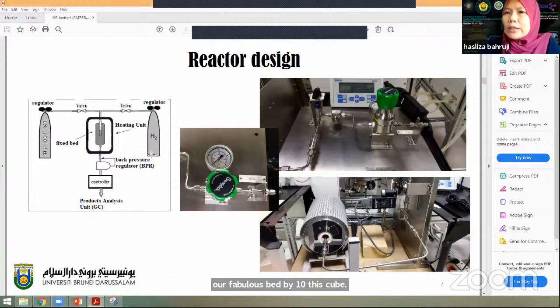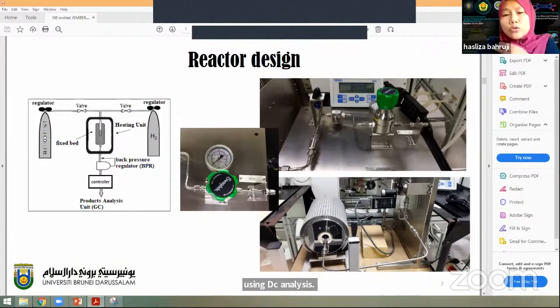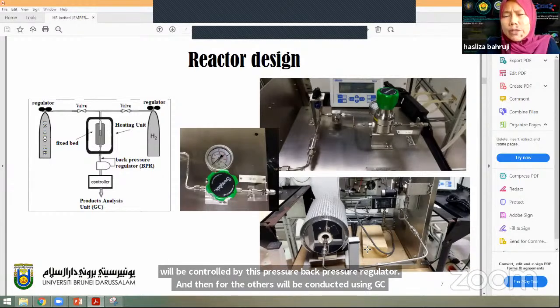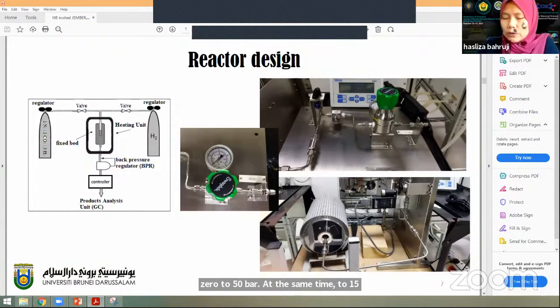We have a flow of hydrogen gas. This is very crucial for the pre-treatment of the catalyst. And also we have our mixed gas. In this case, we varied the ratio of the mixed gas from 1 mole of carbon dioxide to 3 moles of hydrogen, and we have nitrogen gas as a balance gas. The pressure of the catalyst bed will be controlled by this back pressure regulator, and then further analysis will be conducted using GC analysis. So this is a simple setup that allows us to screen the catalyst from 0 to 50 bar, and at the same time from 50 degrees Celsius up to 450 degrees Celsius.